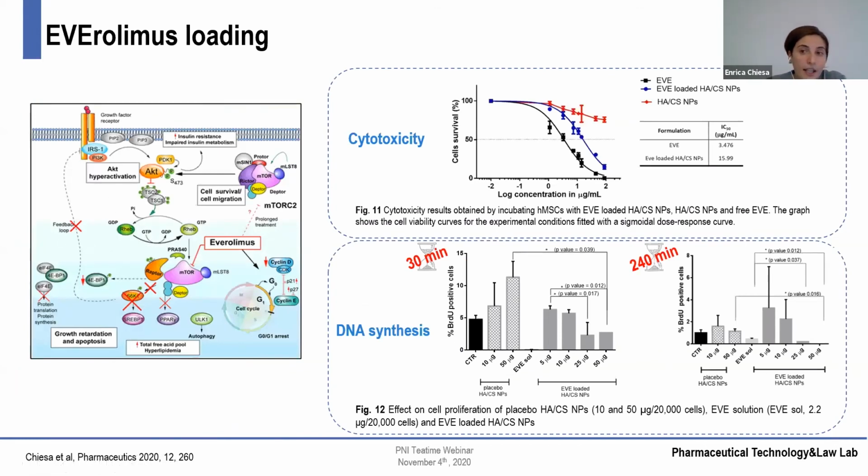Finally, we tested the effect of everolimus loaded nanoparticle on human mesenchymal stem cells. First, the cytotoxicity by MTT assay, and as you can see here, the placebo nanoparticle did not show any toxic effect, confirming the well-known biocompatibility of the raw polymers. Instead, everolimus solution is 5 times more toxic than the nanoparticle counterparts.